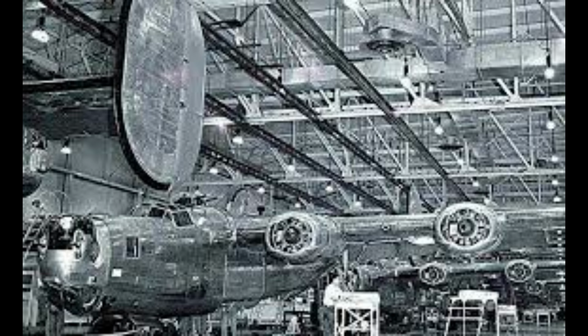The metallurgical laboratories at Willow Run examined the damaged components under microscopes. They could see the scoring patterns clearly. The scratches ran in consistent directions, matching the die movement during stamping. Some gouges penetrated deep enough to remove measurable material. The metal surrounding the damage showed signs of work hardening where the die had compressed it excessively. In the most severe cases, the aluminum showed evidence of galling, where the harder steel had actually torn microscopic particles from the softer aluminum surface.